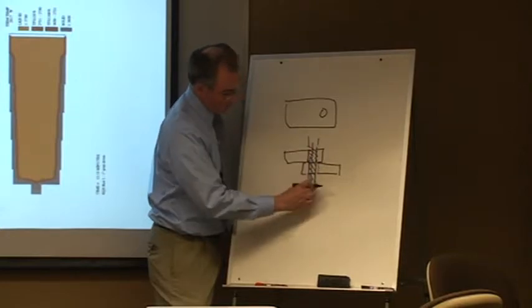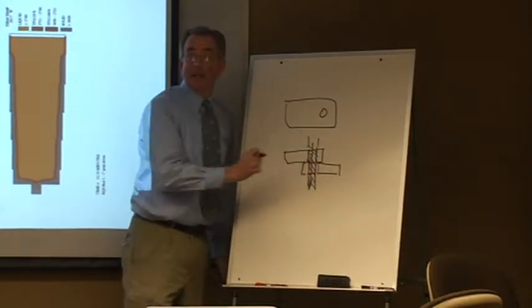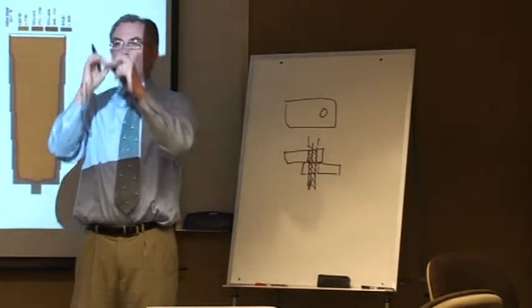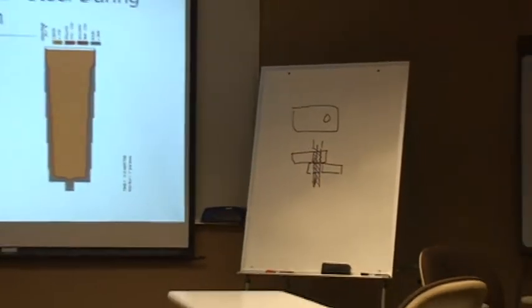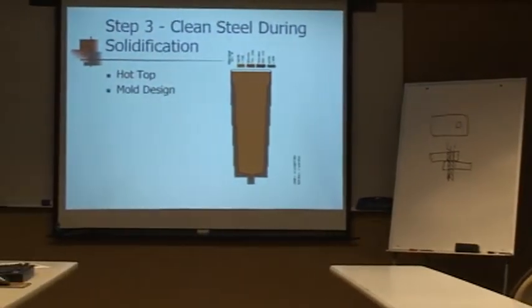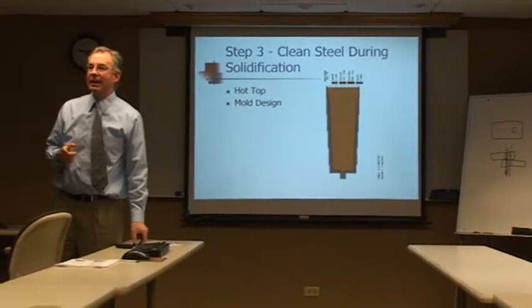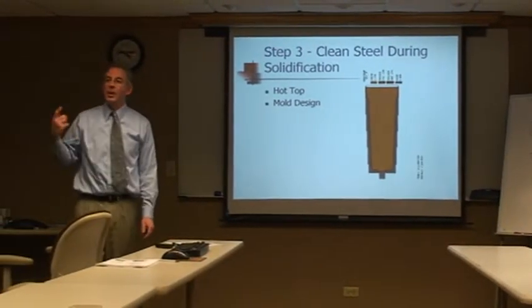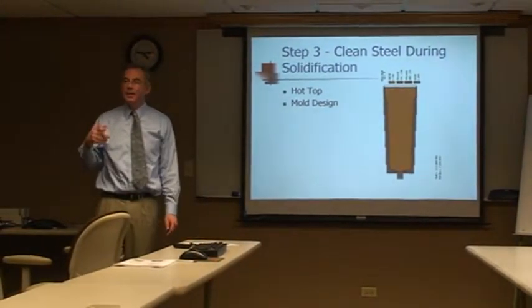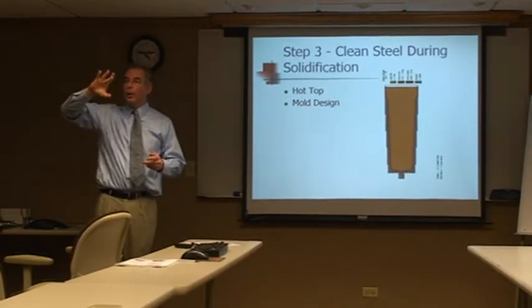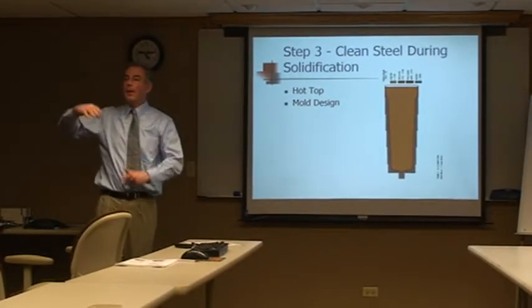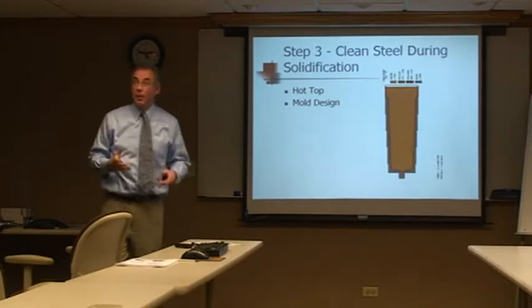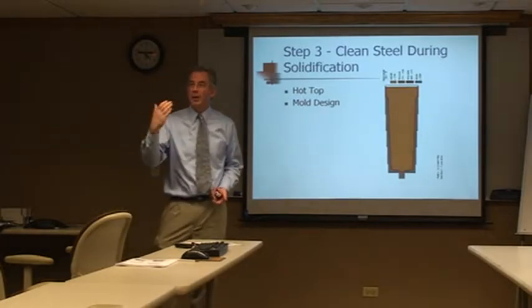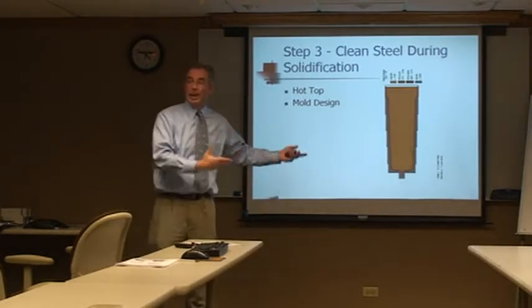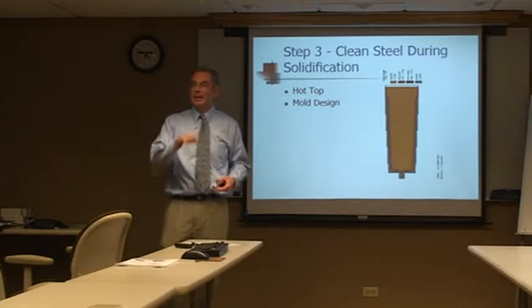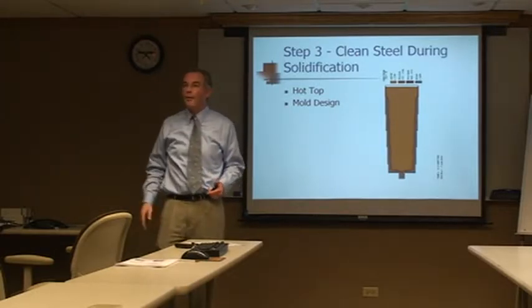So this would be wide open, and then we can adjust these slide gates, and basically by aligning the holes, we can control it. Now, what we do also is we now automatically feed that data, and we're sampling that pouring speed every 30 seconds. So we end up at the end of the heat with a very nice profile. Obviously, our operators, our steel pourer, is monitoring the process himself visually, standing right there, making the adjustments as needed. But we also end up with a very good profile showing up.